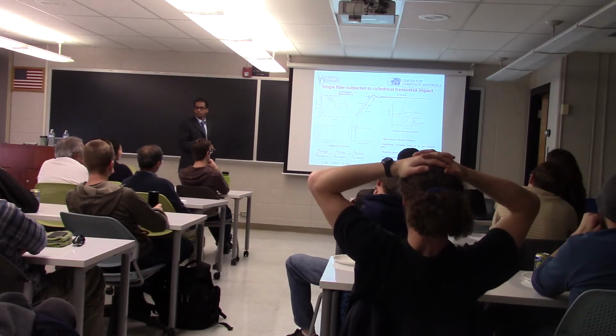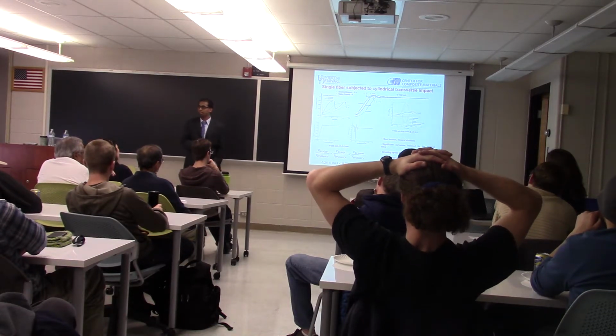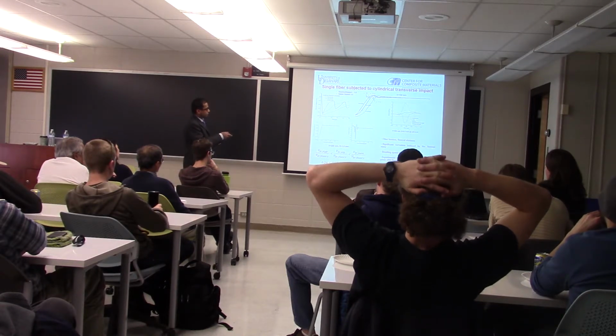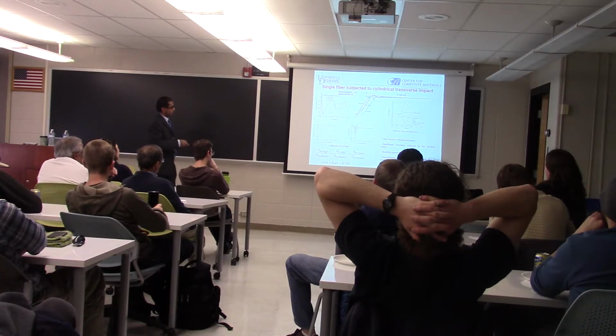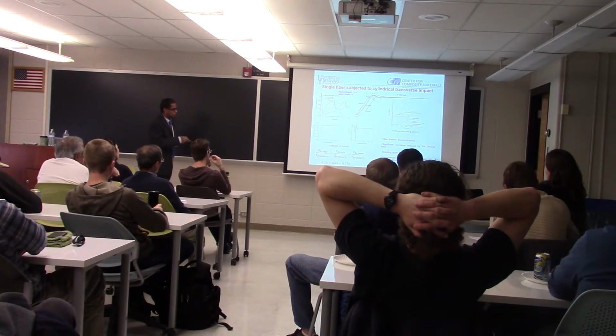The lower bound is based on a max principal failure stress criterion, and the upper bound is based on a membrane stress failure criterion, that is, the average stress acting in a fiber cross section. For the max principal failure stress, failure is always predicted at the point where the curvature is maximum, and all the action is happening within the projectile radius.